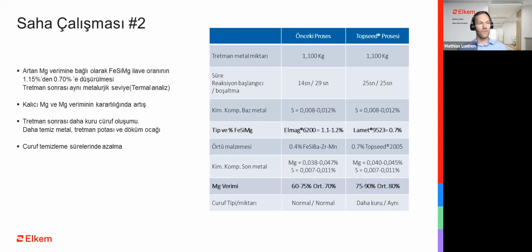Increased stability of residual magnesium and magnesium yield is also a result. And again, drier slags after treatment, cleaner iron, cleaner treatment ladles and pouring furnaces are results. And also, again, don't forget the reduced deslagging time, which is important for practice in a foundry. Next slide, please.